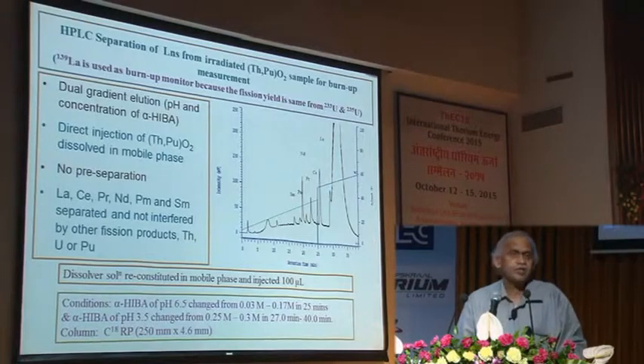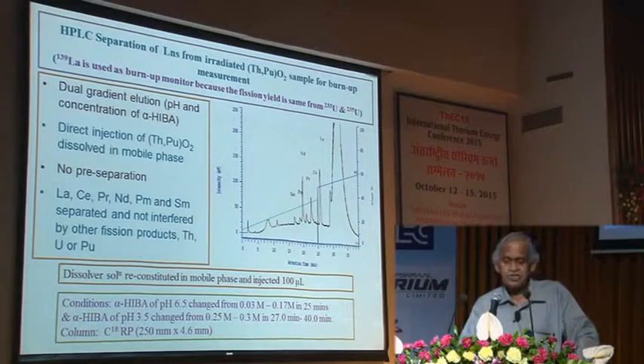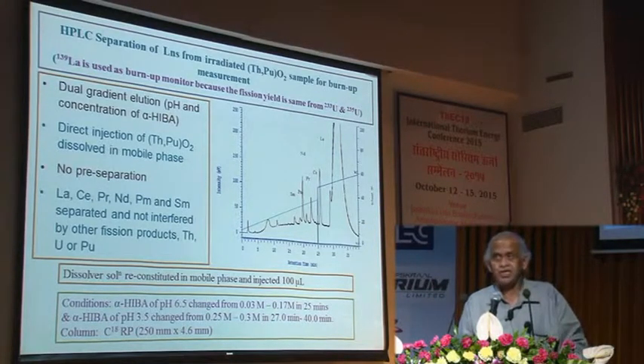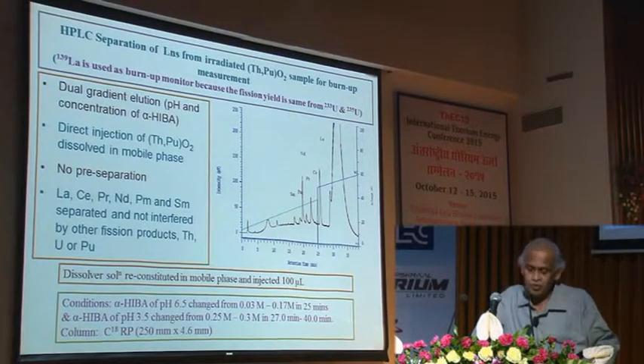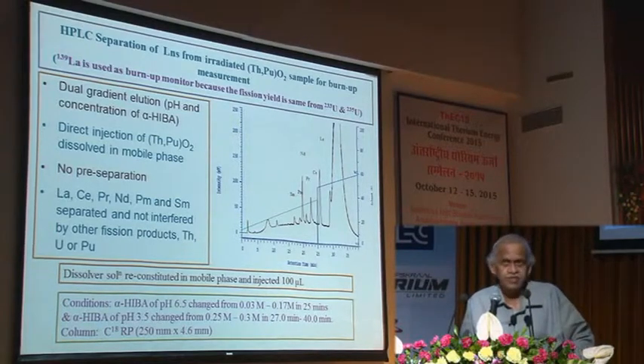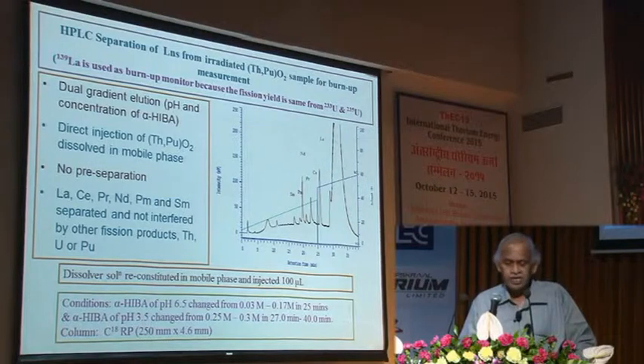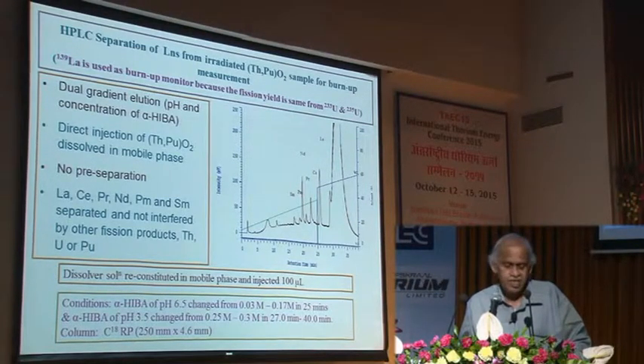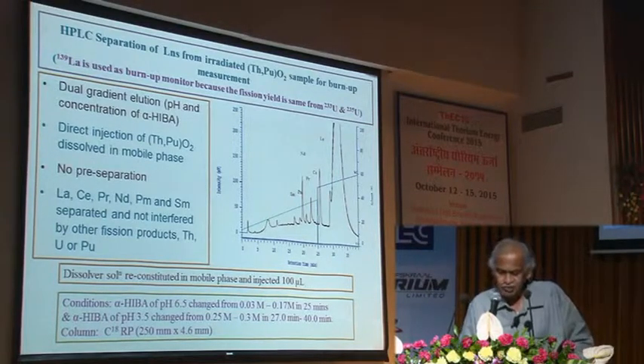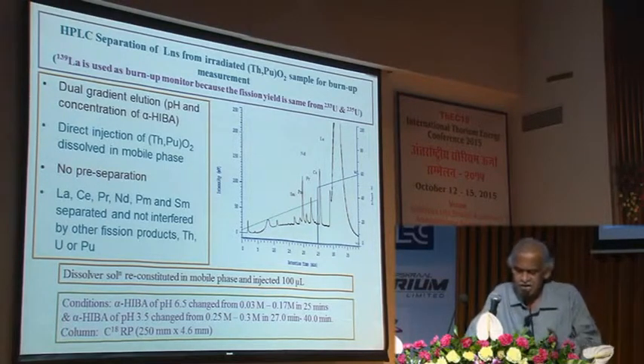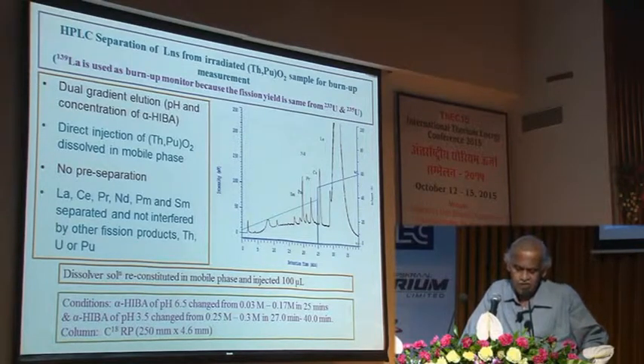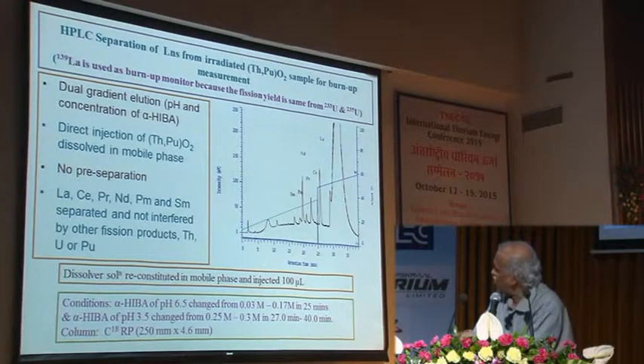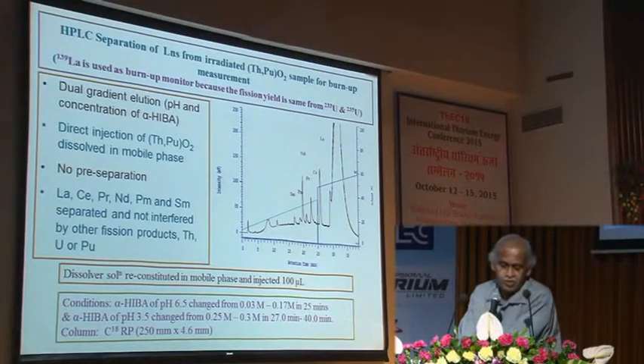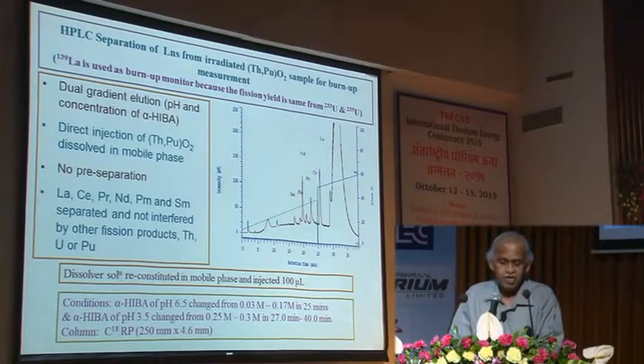that we have employed. And we also use high performance liquid chromatography to develop a method for the determination of burn-up, and there we have used lanthanum-139, not neodymium-148, which is the normally used isotope in uranium plutonia based fuel materials. For thorium plutonium, we have identified lanthanum-139 as the ideal burn-up monitor because the fission yields between uranium-233 and uranium-235 are more or less the same, and the developed technique could comfortably be used for determination of the total separation of total rare earths as well as lanthanum-139. The conditions that have been optimized are given here so that people could make use of this developed technology to separate lanthanum for the burn-up determination.